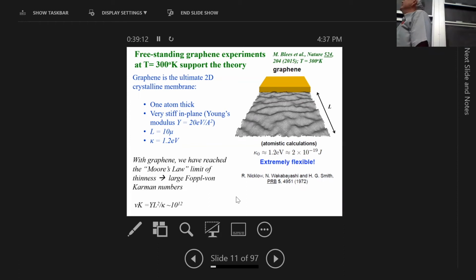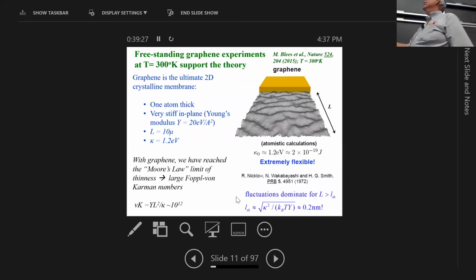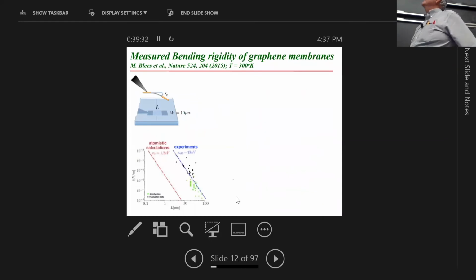Putting in the size and the bending rigidity, which is about 1.2 electron volts, comes from density functional theory, and so forth. This is the Foeppl-von Karman number that comes out, 10 to the 12th. And as I said, the L thermal is 2 angstroms at room temperature. So what happens? Well, I'll talk about other things for the rest of this colloquium, but what they found was by measuring the bending rigidity, by looking at how this weighted pad got deflected. Standard experiment actually done by Galileo. He did the first theory of cantilevers, but not for graphene at room temperature.